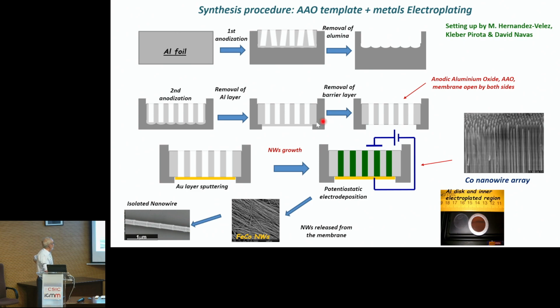Very, very simply, I would like to say that we start with a highly pure aluminum foil, typically 1 inch in diameter, and then by two anodization processes, we get a membrane opened on both sides. Then we sputter a tiny layer of gold, and we use this gold layer as an electrode for the electrodeposition. We have a picture of cobalt nanowire arrays, and in the very last years we have been interested particularly in the study of individual nanowires.